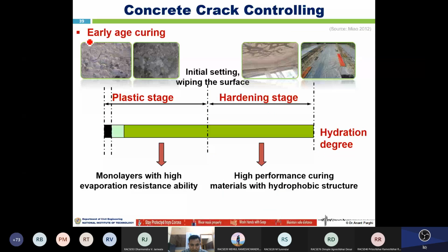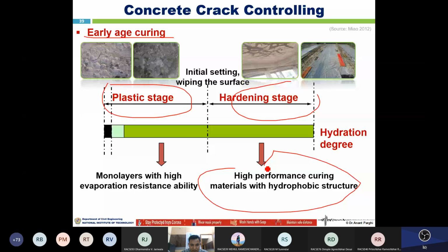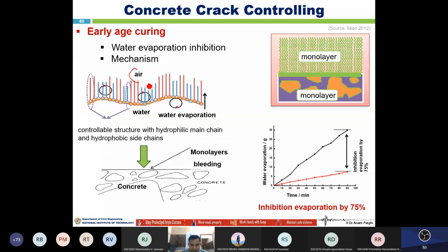You also have to provide early age curing. Here in the plastic stage and the hardening stage, monolayers with a high evaporation resistance ability and the hydration degree, like high performance curing materials with a hydrophobic structure, is used. With air and water here, water will evaporate, so you can save it with the monolayer. You can see the inhibition of evaporation at the initial time by 75%, which reduces cracking.